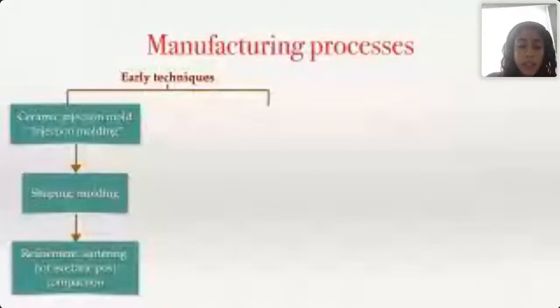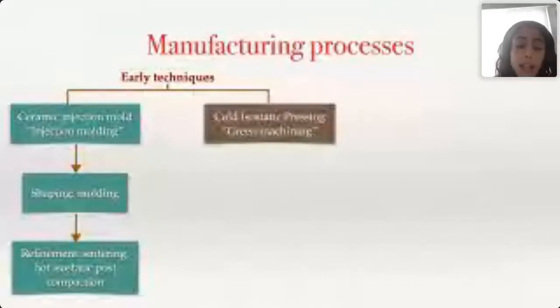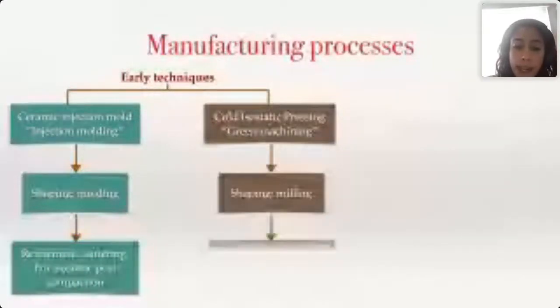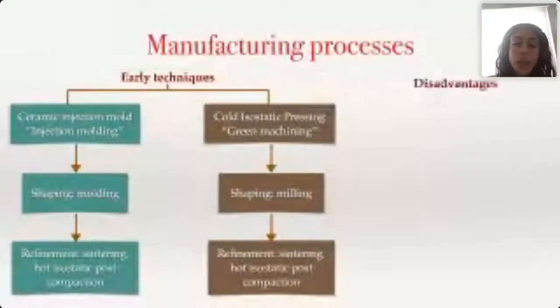So what are the different manufacturing procedures? One is ceramic injection molding. It starts with injection molding of the material, then shaping, then refinement, sintering, and hot isostatic post-compaction. The second technique is green machining - shaping of the material by milling, then sintering and hot isostatic post-compaction.